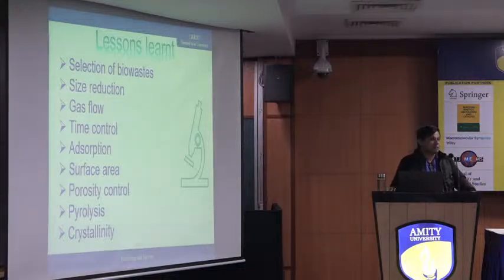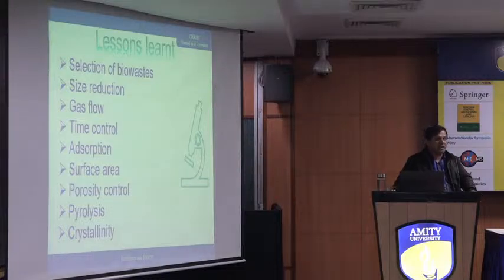The next is gas flow. How much gas should be passed? Because you are conducting all these experiments in the presence of nitrogen, an inert gas. More nitrogen is again an adverse effect. Less nitrogen will allow oxygen to pass through. Then again you will end up with a lesser amount of carbon nanoparticle. So how to control the gas?